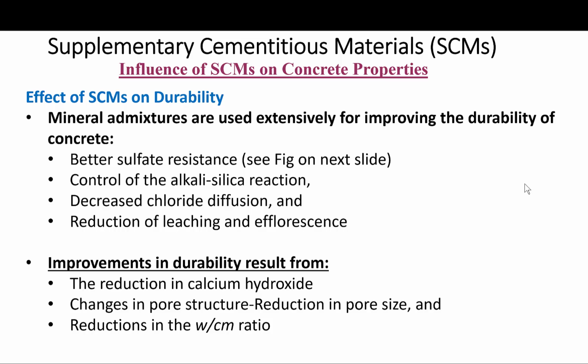Also, sulfate ions can enter the concrete more readily, and calcium hydroxide becomes a convenient source of calcium to concentrate and form gypsum, and eventually ettringite. So the removal of calcium hydroxide helps with that too.